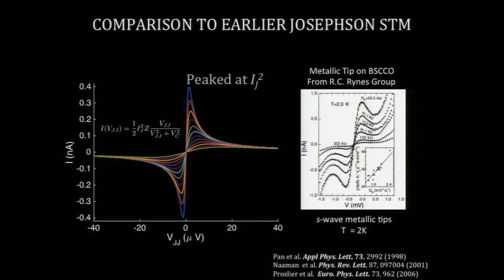He does state in that paper, using an S-wave tip, what he was probably seeing was some distortion of the crystal lattice, which gives rise to a bit of S-wave superconductivity in the system. That was his explanation. We're still not quite sure to what extent S-wave to D-wave can couple or not. But what he was unable to do, because he had to jam the tip into the surface to get that, is he couldn't scan. He couldn't actually move the tip and start to look at these curves as a function of spatial position.